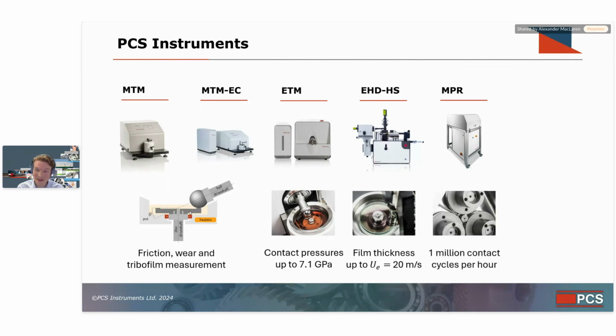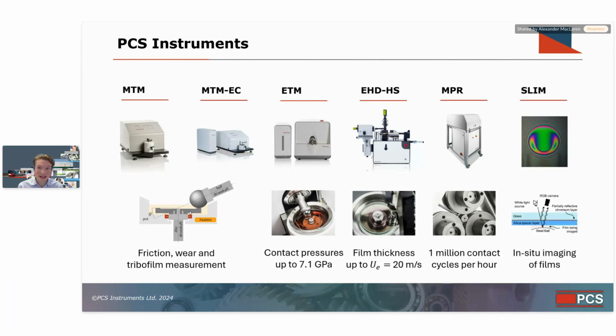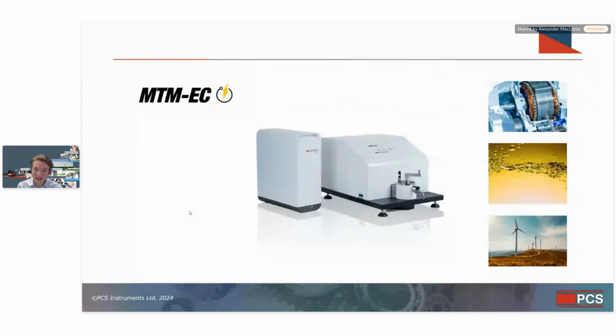And finally, our fatigue tester, the MPR, or micropitting rig, is able to generate 1 million contact cycles per hour. And in applications where you might have 100 million contact cycles over lifetime or higher, this means that in an accelerated test, you can representatively simulate that condition in a realistic amount of time. So between them, these rigs provide a really important suite of techniques that allow us to develop the next generation e-fluids. And finally, our optical technique, the space layer imaging method, or SLIM, enables in situ imaging of both tribofilms and elastohydrodynamic films. And so when they're behaving strangely as a result of electrical contact or as a result of starvation at very, very high speeds, you can optically see what's going on and then start understanding those mechanisms and optimizing those lubricants.